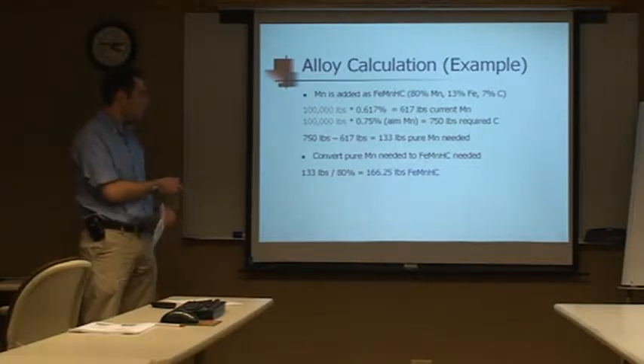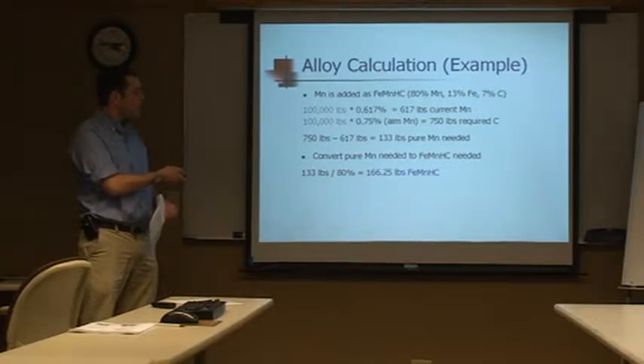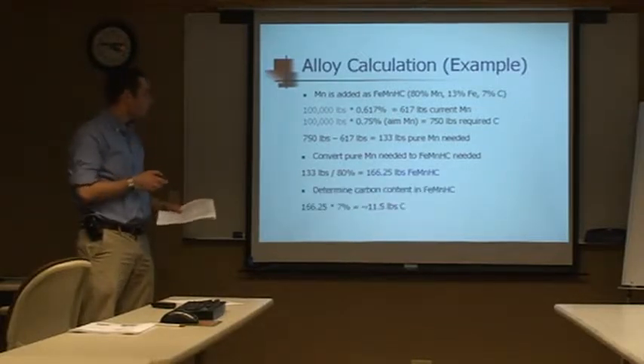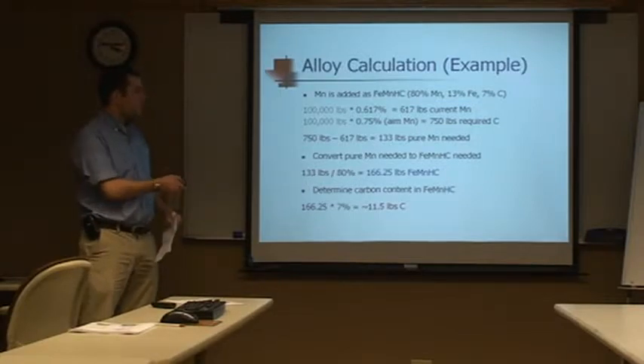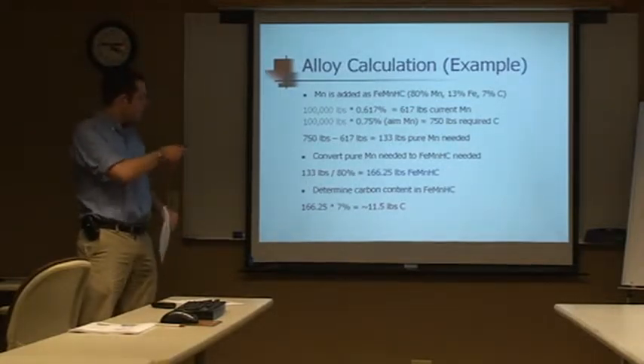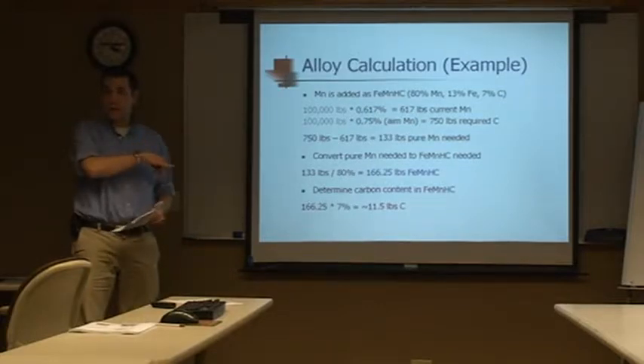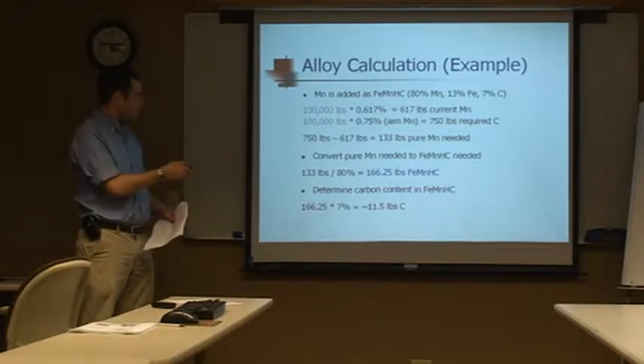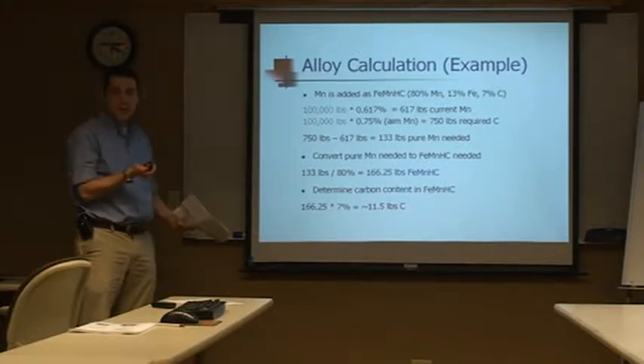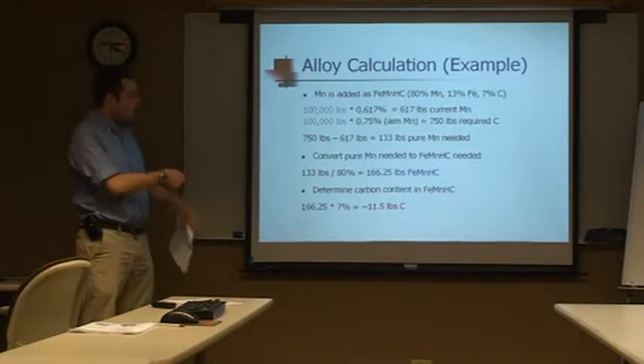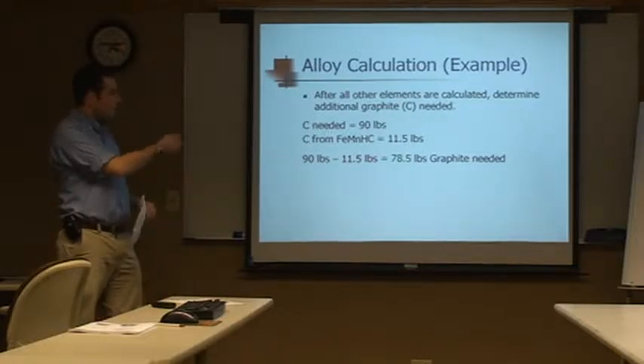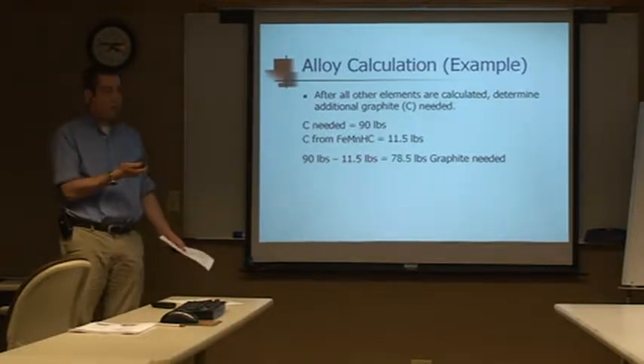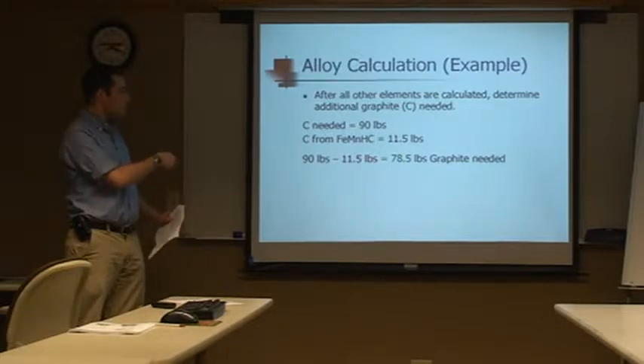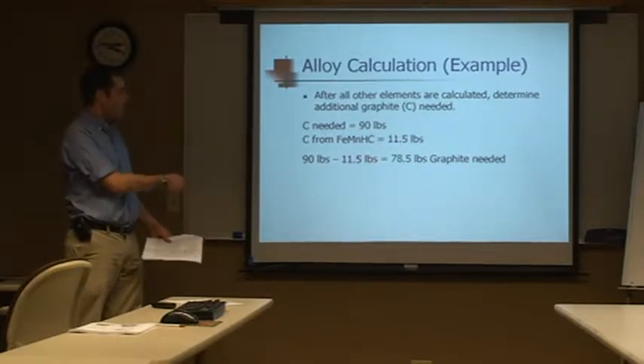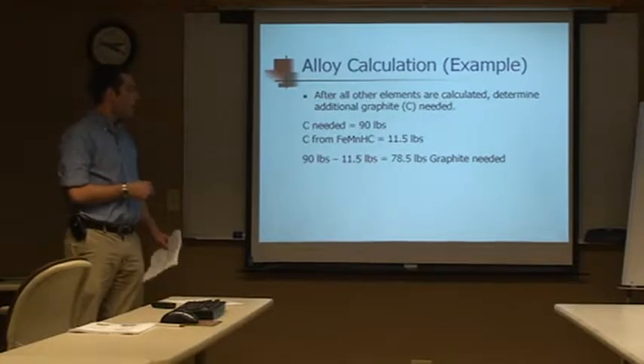So we just divide by the amount of manganese in the ferromanganese and figure out we need 166 pounds of ferromanganese. So now we have to determine, since there's a carbon component to the ferromanganese, how much carbon we're adding when we add in our ferromanganese. Doing the same thing, we figure out it's 11.5 pounds of carbon powder. So we take that number and we go back and subtract it from the 90 pounds we would need to add as pure carbon. And so since these are the only two things we're adding in, we can now add in our carbon as 78.5 pounds of graphite.